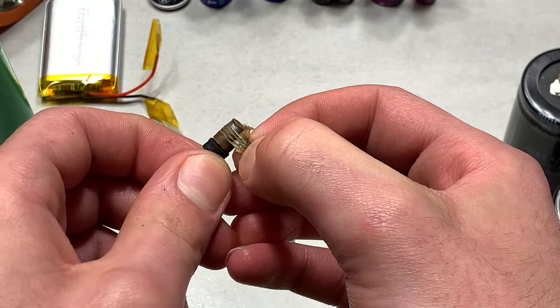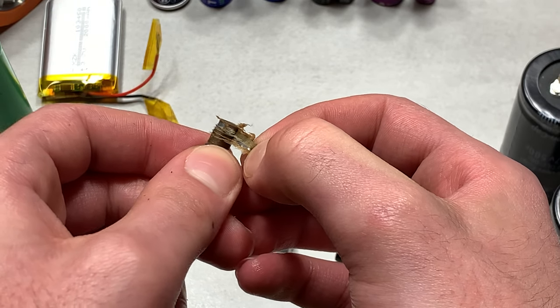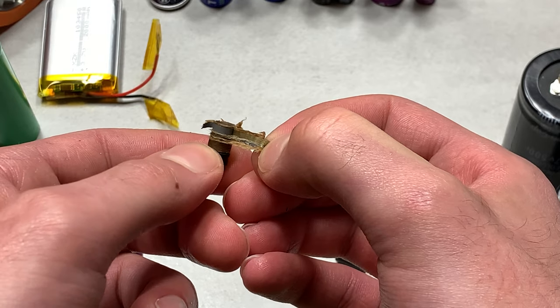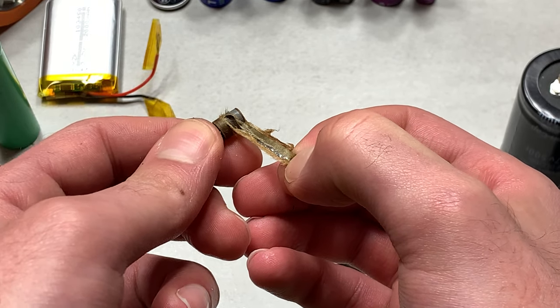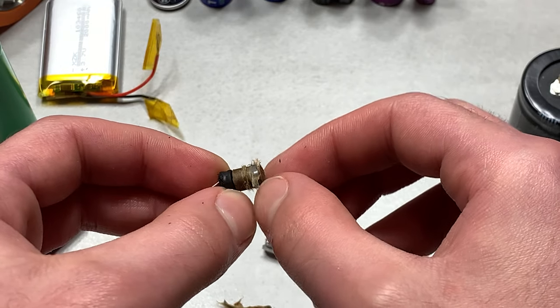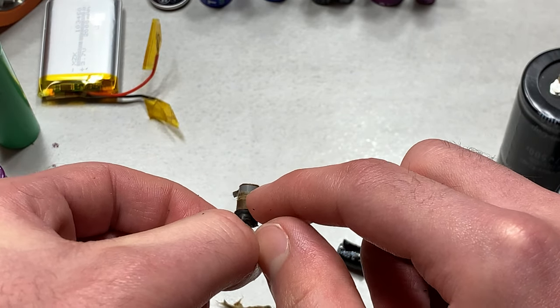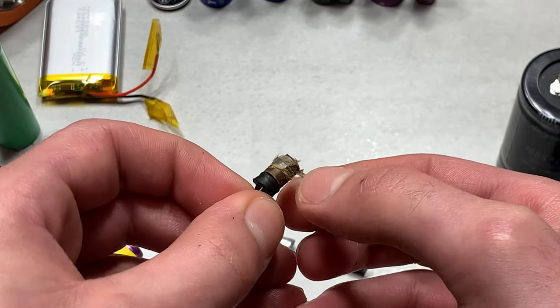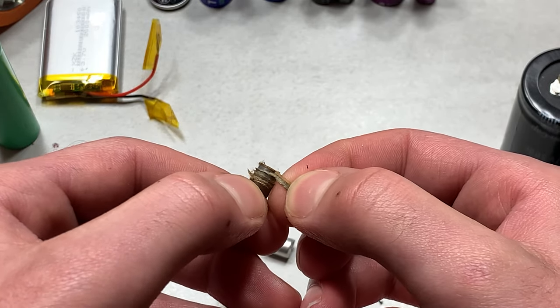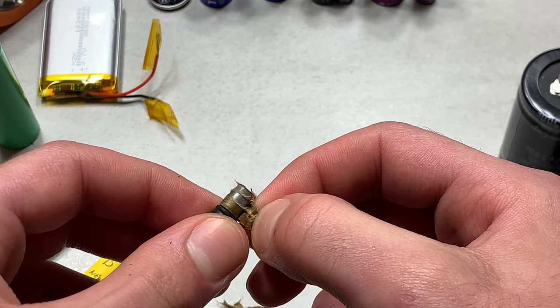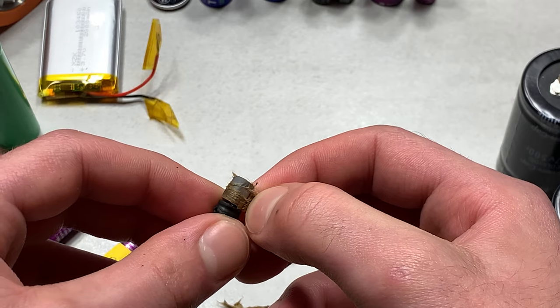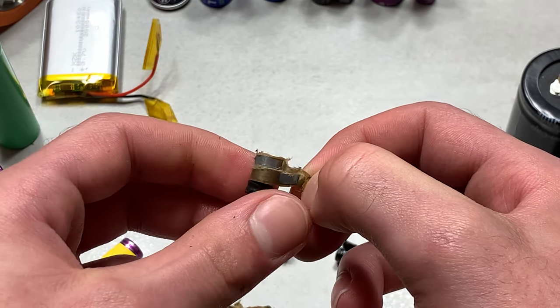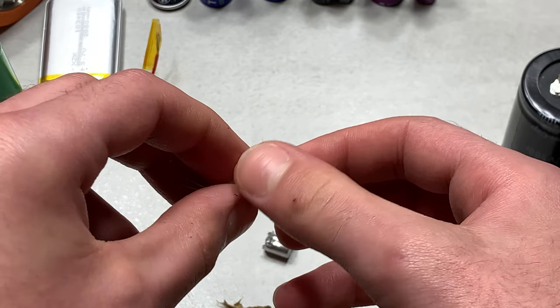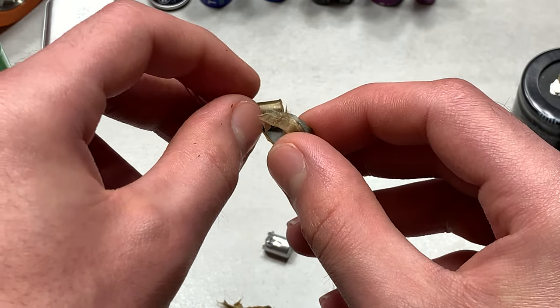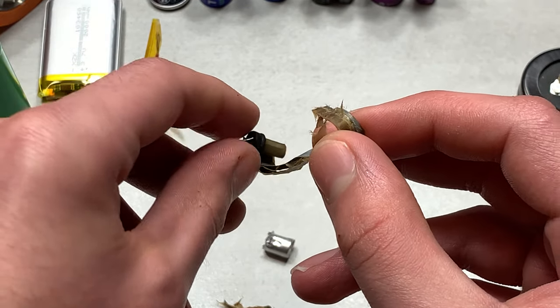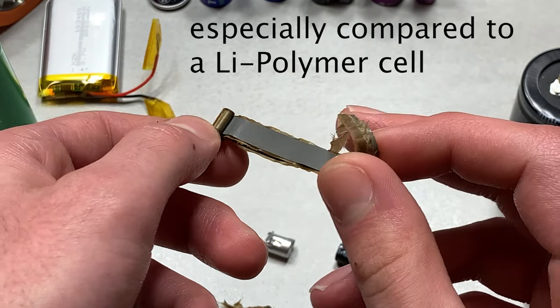So essentially, as you can see, it's like a paper that's mixed with a gummed adhesive type material. And as we unwrap this, we can see the alternating layers of aluminum with an aluminum oxide dielectric on it. And then we can see it transitioning to the bright, unoxidized aluminum as we peel the layers off. So this is what I mean with the inside of the capacitor having a very high surface area. And that if the supercapacitors are made in the same way, this would really reduce the charge density.